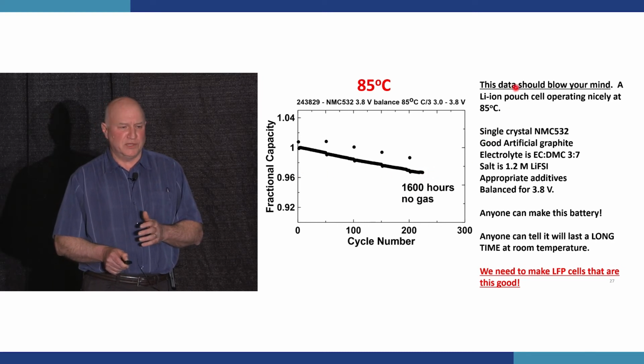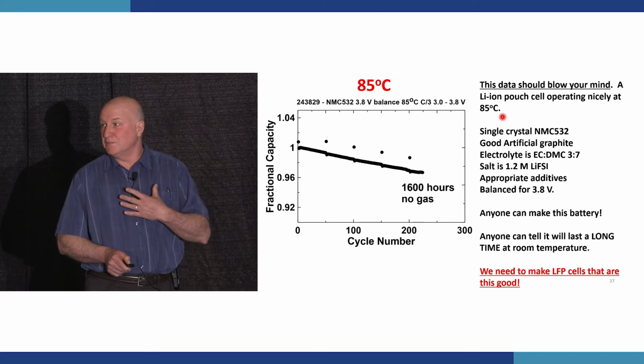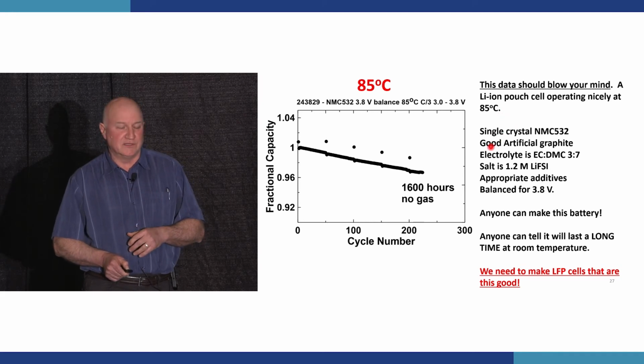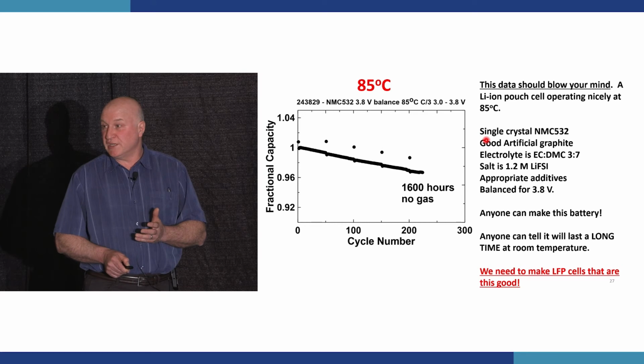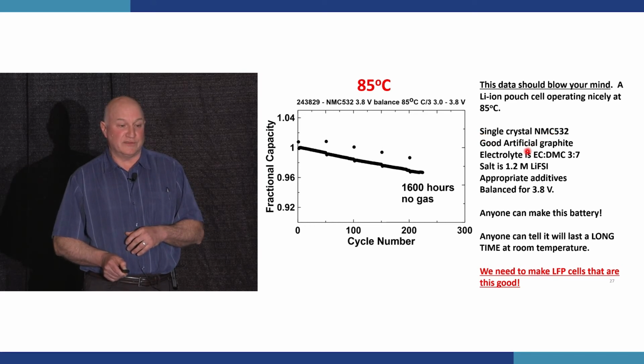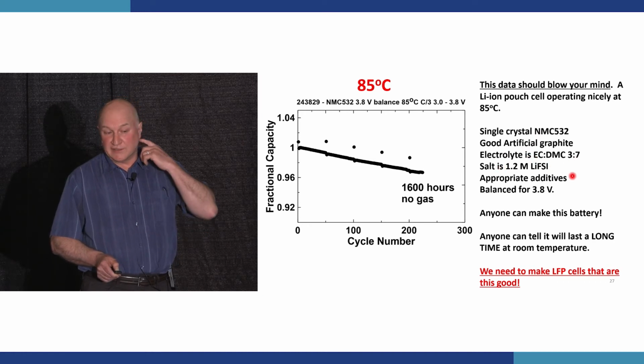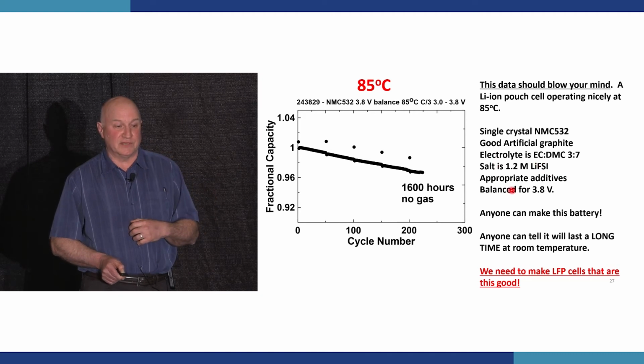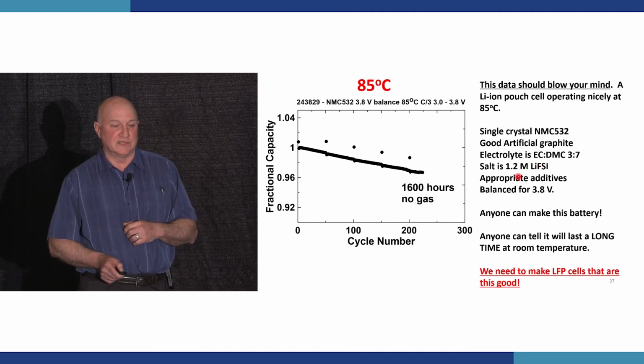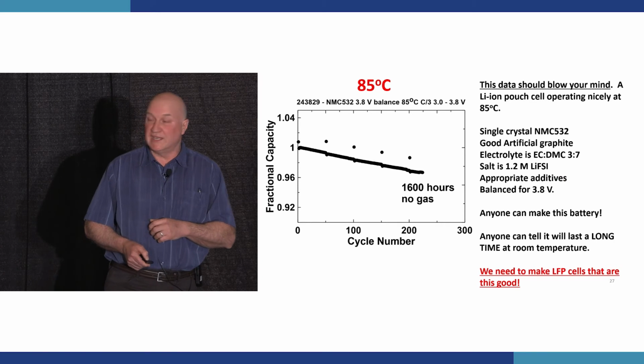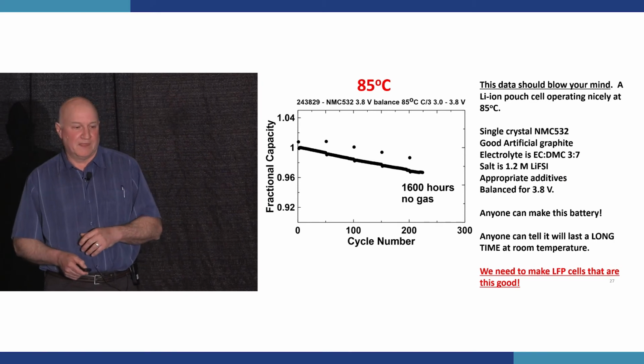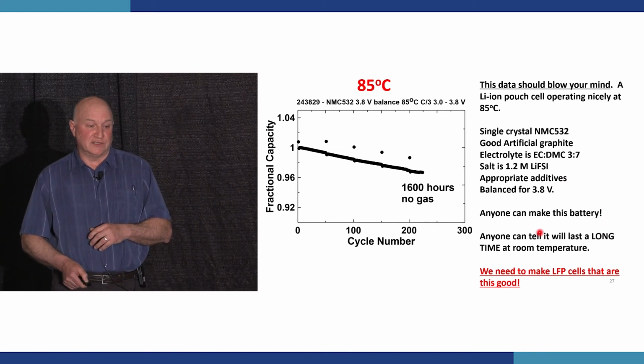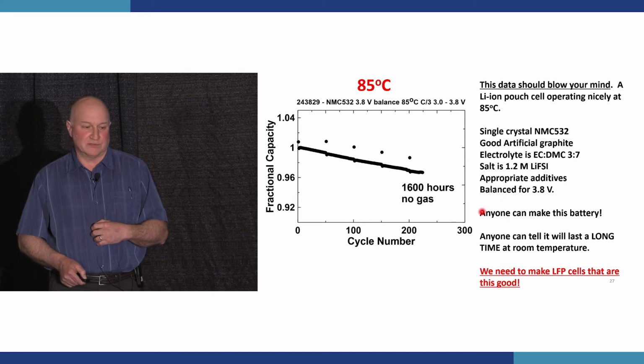These cells, this should blow your mind. It blew my mind. I couldn't believe this was happening. And it's a simple cell. Anybody can make this. Single crystal 532, artificial graphite. The solvents are just ethylene carbonate, dimethyl carbonate. The key here is the salt is LiFSI and low voltage operation, balanced for 3.8 volts, appropriate electrolyte additives. Anybody can make this thing. And anyone can tell it's going to last a long time at room temperature.